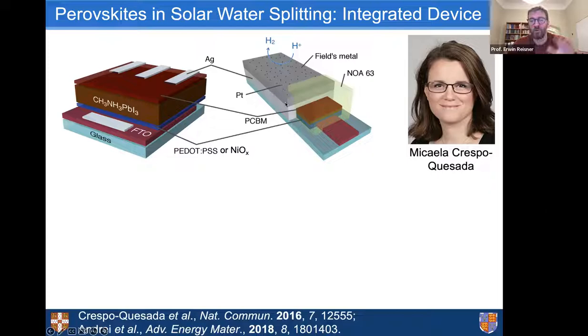But actually the most important thing from this device, we just started then sealing it off with the Field's metal. And you just have to be careful that the iodide is not in close contact, for example, with silver, because it would rip out some of the halides. But otherwise, Field's metal just on top, heat up, seal off, and that's it. And then it's even quite reducing. So if you take the Field's metal protected photocathode and dip it in a platinum precursor solution, it will actually even auto reduce the platinum on top of your Field's metal. So you have the device assembled.